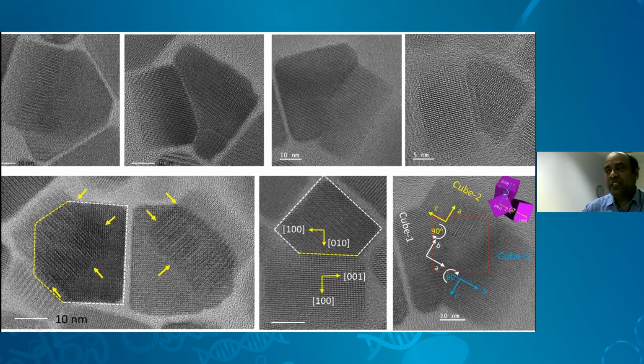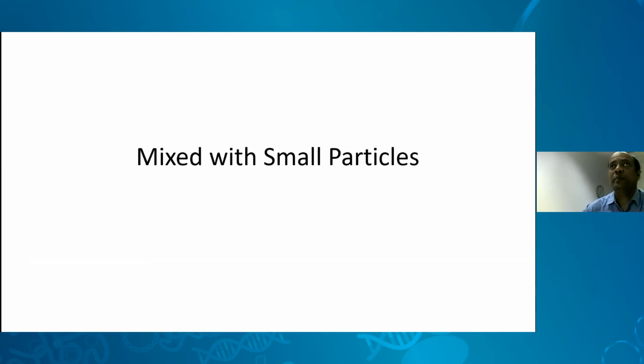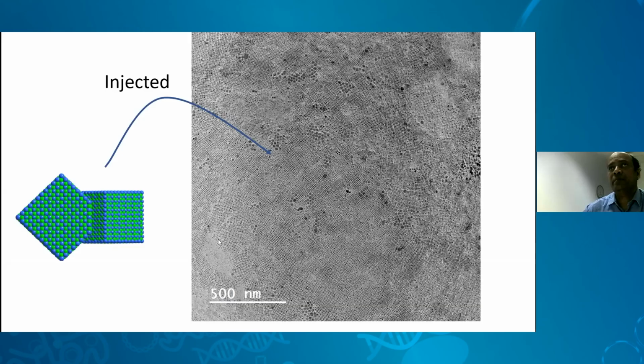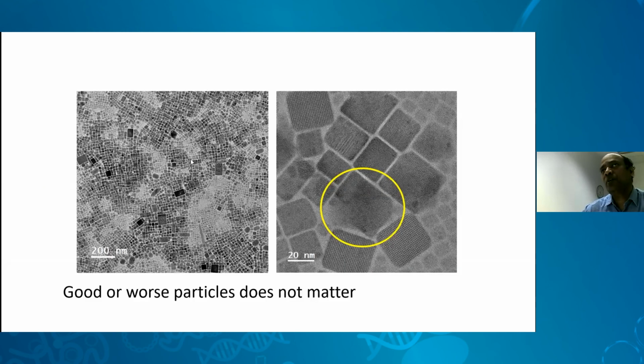So now what happens, these new structures, we put them out and we mix with any platelets or the cubes which have been reported. So we put it out, we see the larger size, we show inside this TEM picture the larger size, what you see here is this type of coupled structures. When we injected, these structures are so hungry that they try to eat everything they find in the cesium lead halide nanostructures. So it tries to eat it out. As soon as it sees something, it does not matter whether these are good or bad, small or something like that.